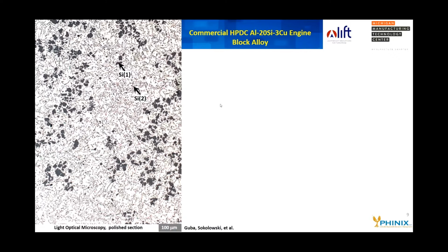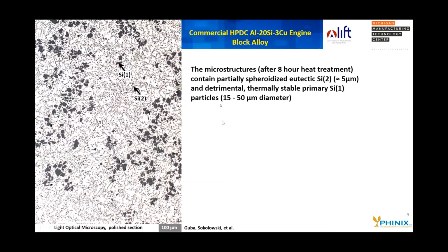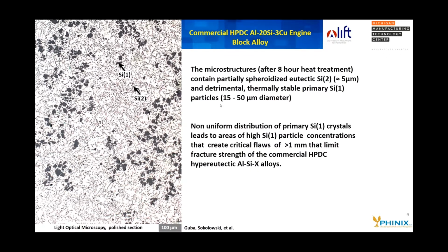It is already heat treated, and it is dominated by large primary silicon particles and partially spheroidized secondary silicon particles. The secondary silicon particles are about 5 microns in diameter, and the primary particles are 15 to 50 microns in diameter, but their non-uniform distribution creates critical flaws that are over a millimeter, and that limits the fracture strength of such a commercial alloy.